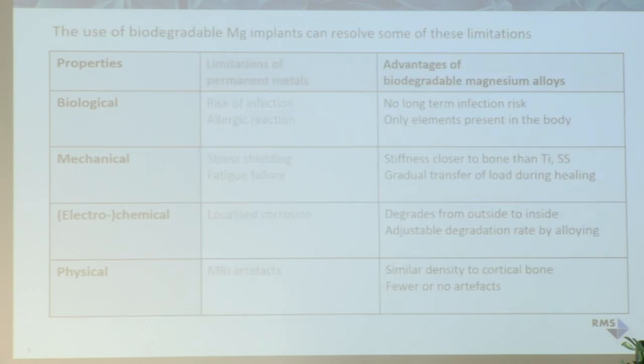Now, the use of biodegradable magnesium metal can help to resolve some of these limitations. For example, the risk of infection is not there because the surface degrades and is no longer there. So you have no long-term infection risk. On the other side, allergic reactions are not a problem either because the new generation of magnesium alloys has only elements which are already in your body, like magnesium or calcium.